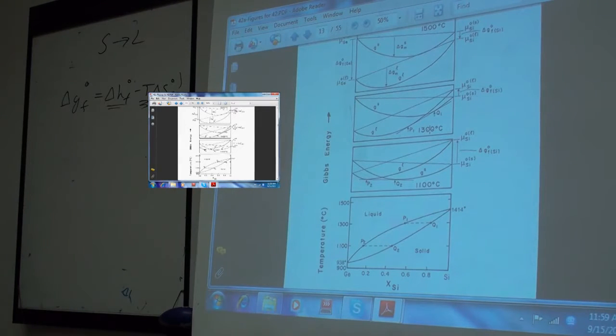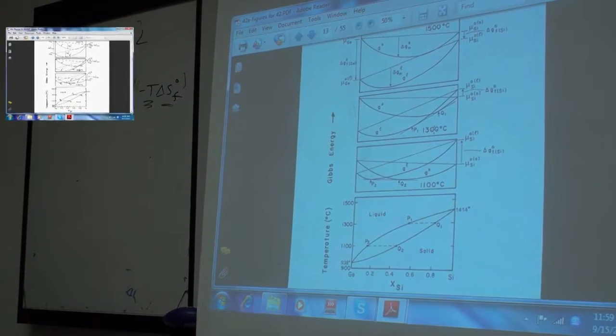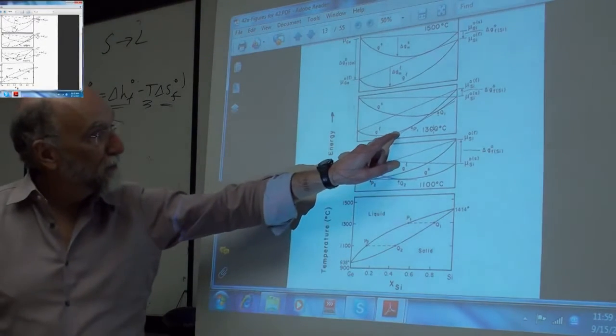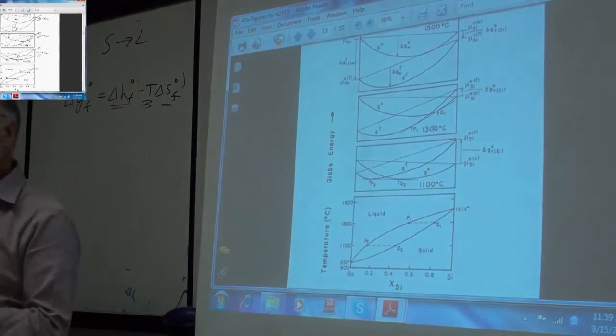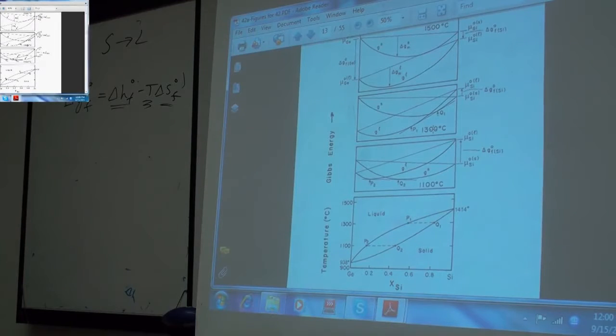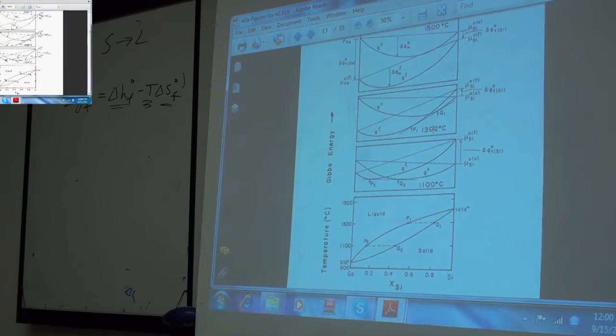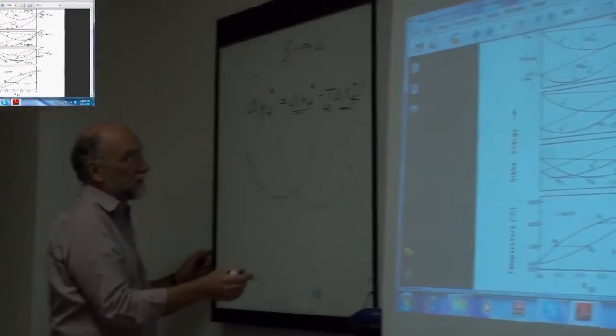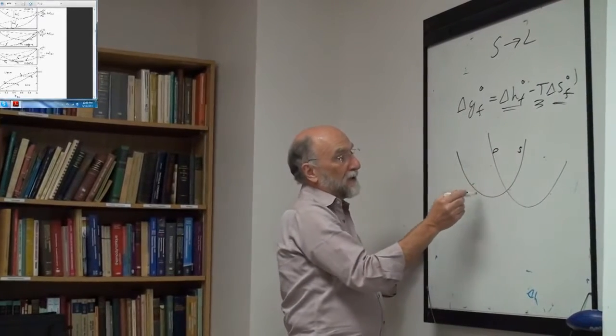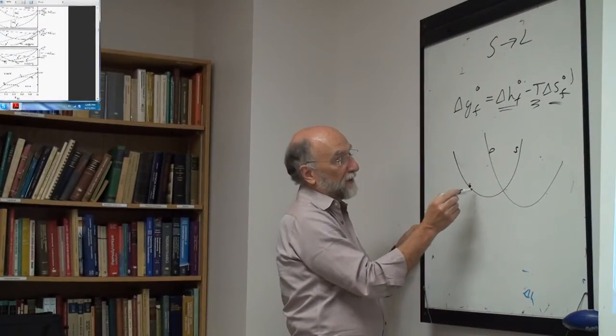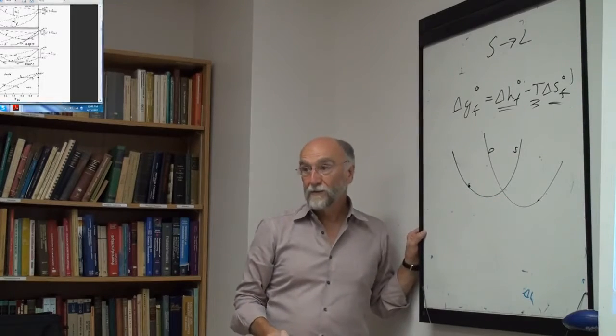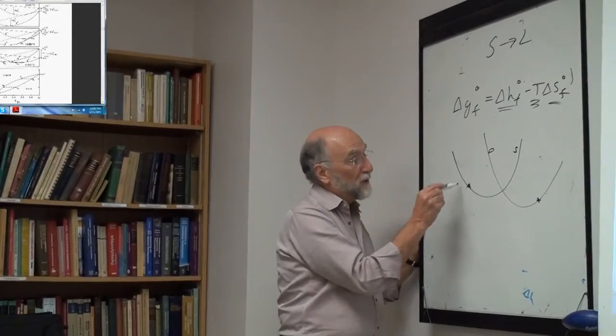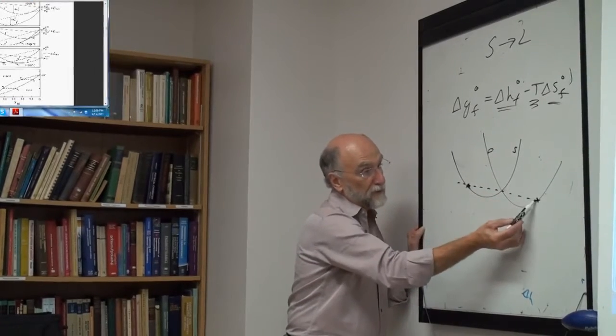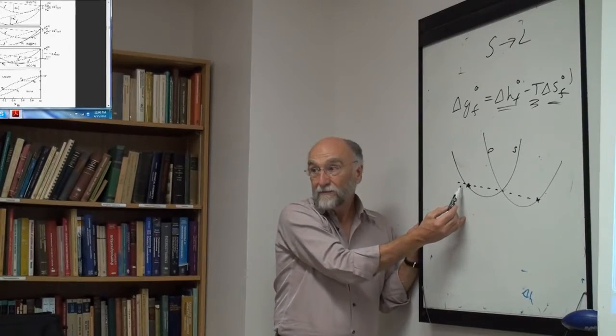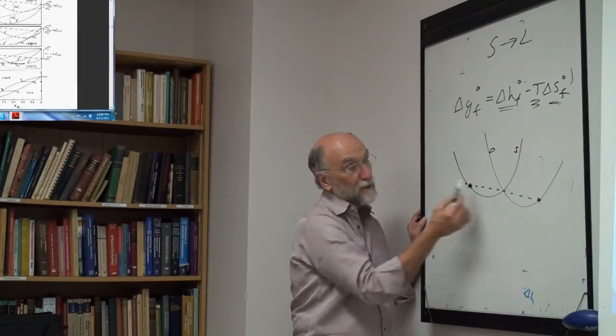Now the criterion for equilibrium is also minimizing the Gibbs energy. So the system wants to minimize the total Gibbs energy. What you're going to have is two phases in equilibrium: one point on the liquid curve in equilibrium with a point on the solid curve. And in between those two points, the system will follow the line. So here's my liquid curve, here's my solid curve, and let's say I have this composition of the solid in equilibrium with this composition of the liquid. So I have a phase here, and a phase here. In between those two phases, the Gibbs energy of the mixture will follow that line, just by mixing. If I have half of this and half of this, I'll be halfway in between.